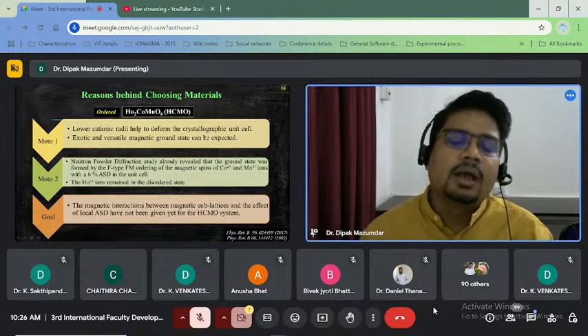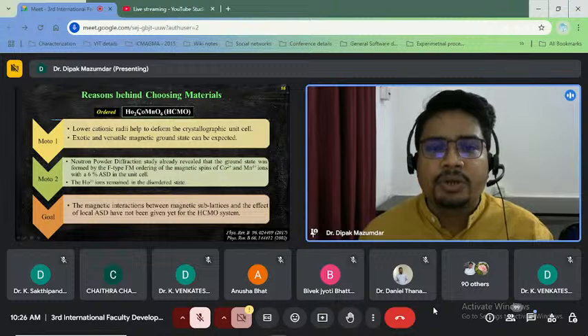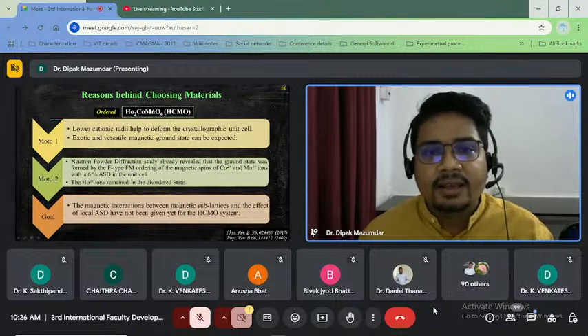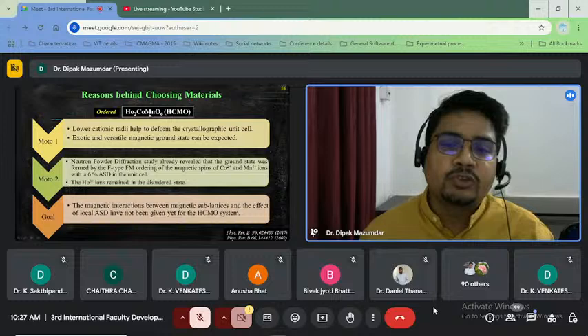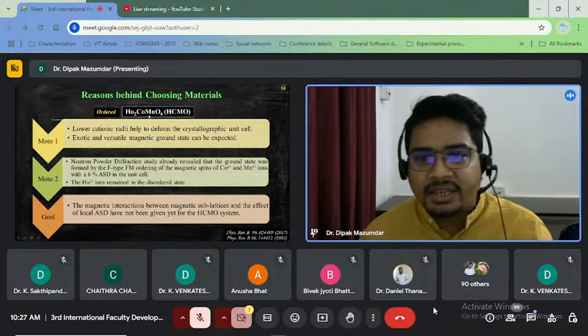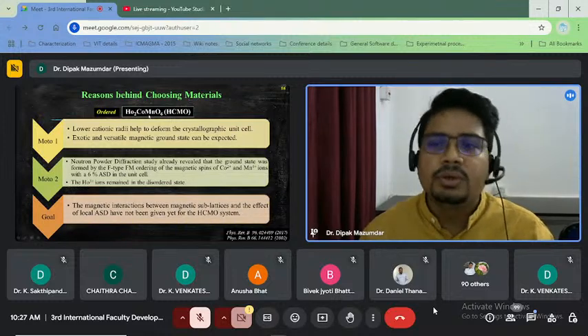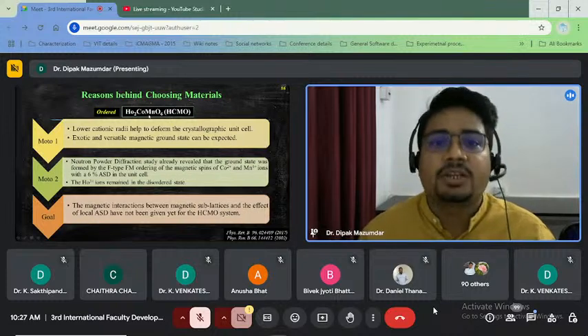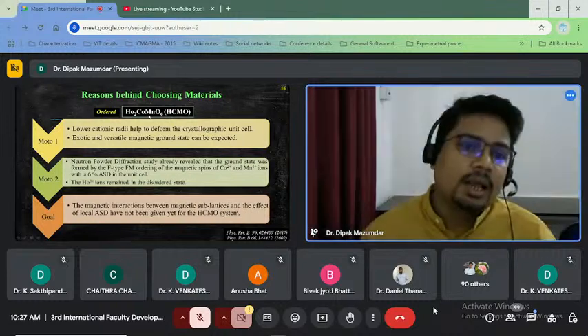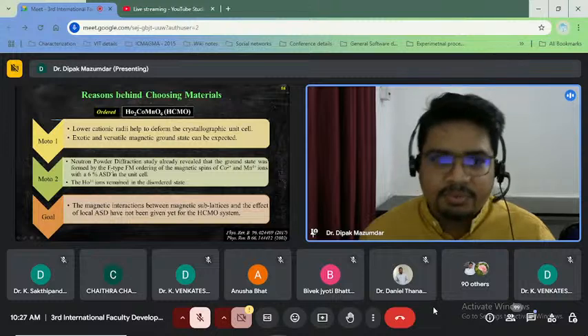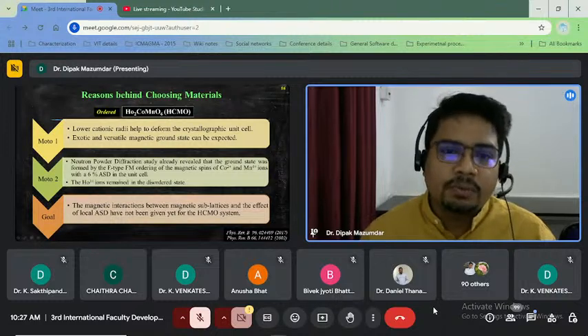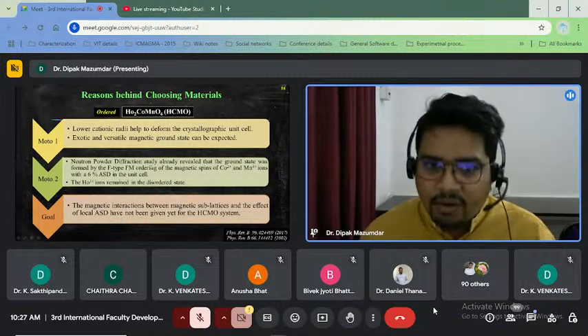As a result, the exchange interaction, or you can say the octahedral angle, between cobalt and manganese will change from the ideal 180 degrees, and this will help us generate some versatile and exotic magnetic properties in the compound.